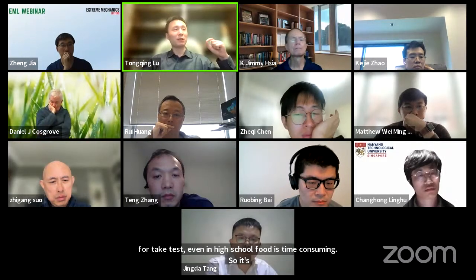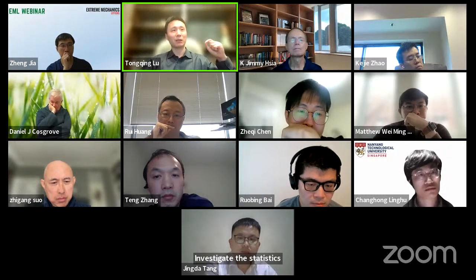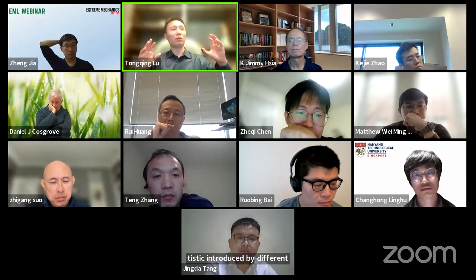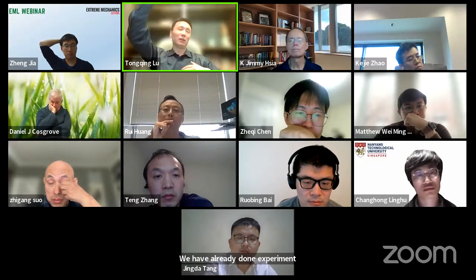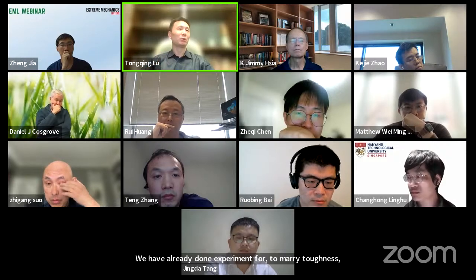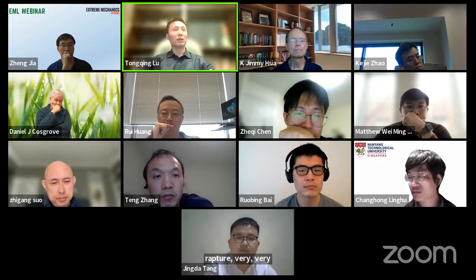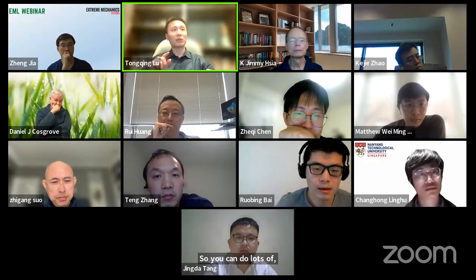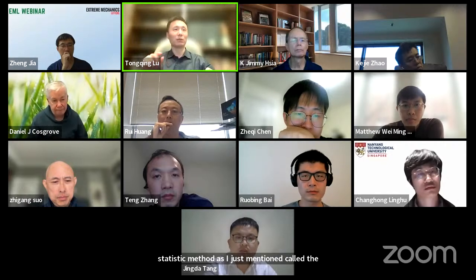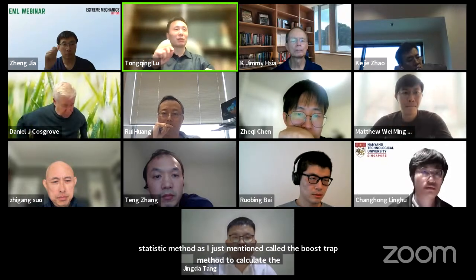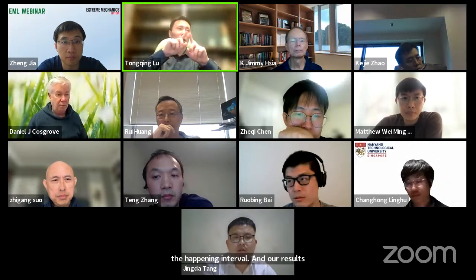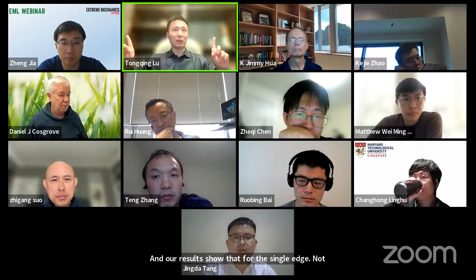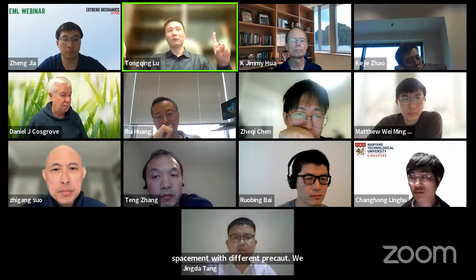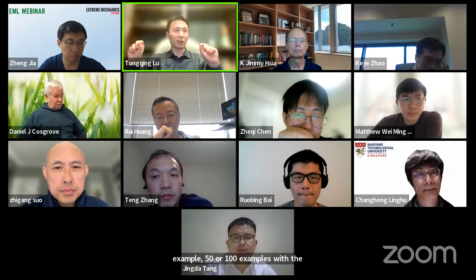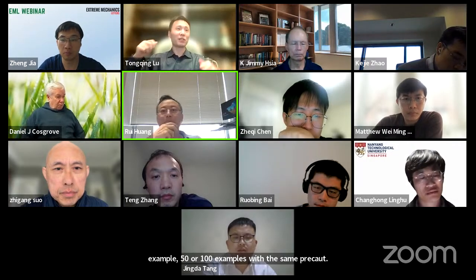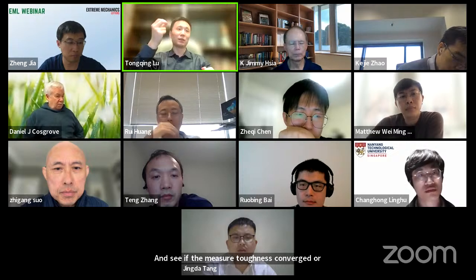So if we investigate the statistics introduced by different pre-cut lengths, we have already done experiments to measure toughness, not fatigue, because you only stretch it until rupture very quickly. So you can do lots of samples. And we also use the statistic method, as I just mentioned, called the bootstrap method, to calculate the toughness interval. Our results show that, for the single edge notch specimen with different pre-cuts, we first prepare, for example, 50 or 100 samples with the same pre-cut, and see if the measured toughness converged or if the confidence interval is narrow enough.